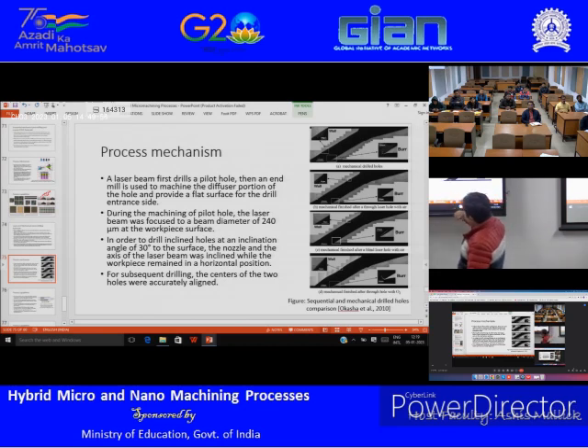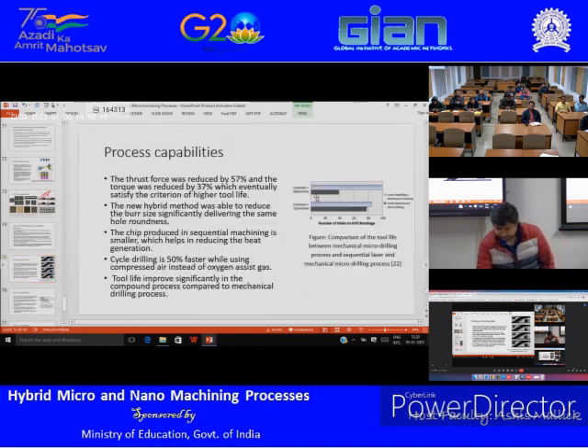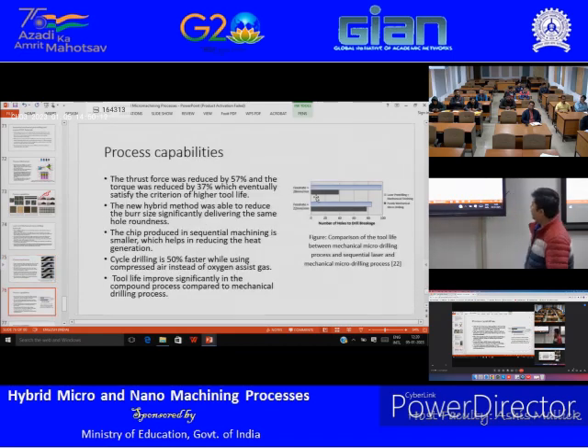So here it shows some comparison. During the machining of the pilot hole, the laser beam was focused to a diameter of 240 micron, and it was done at a 30-degree angle. So the cutting forces were reduced by 57%. That means if you just do mechanical drilling without any pilot laser hole, the cutting forces are much higher.